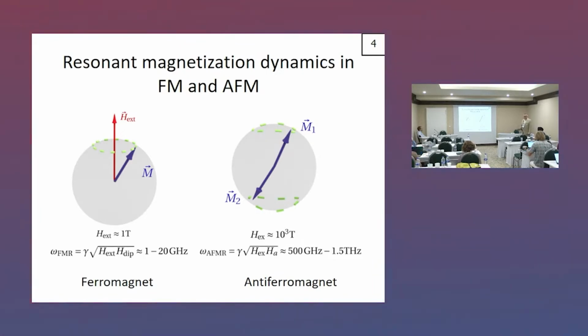If you try to do something like that in an antiferromagnet, we have two directions of magnetization, one sublattice and the other one. If you destabilize one of them, you will actually stabilize the other one. So if you apply the external spin torque or spin polarization which is parallel to the direction of these two magnetizations, the net result will be zero. You will not be able to excite anything. So there is no chance to actually excite the eigenfrequency. If you want to excite something, you need to do something else.